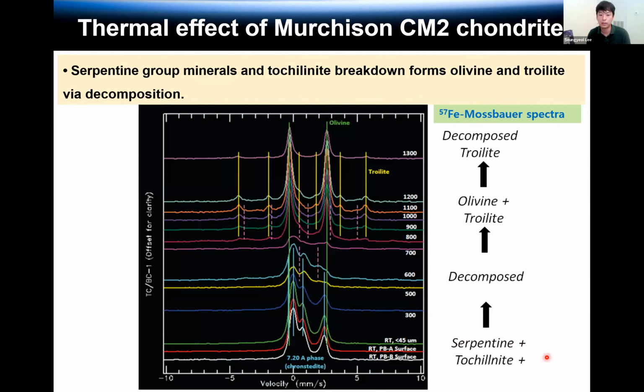So serpentine and tochilinite have iron in the structure. So iron, most of our spectra are also useful to determine the mineralogical changes. So initially, serpentine and tochilinite, most of our peaks, and during the heating, these peaks become broad, which means decomposition happens. At higher temperature, recrystallization happens and then they become the olivine and troilite phases. So most of our XRD very well matches with our heating observation, the TEM.